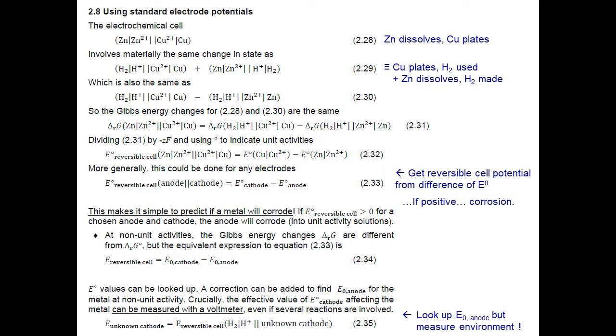But that doesn't matter, because you can see in equation 2.35, what I've done is I've simply said we can measure the equilibrium potential of the cathode on whatever metal we have in our environment. That we just need to use one measurement with a voltmeter connected between a standard hydrogen cell, in principle, and the unknown cathode that we're looking at, and then we know the cathode equilibrium potential. And then that means that with one measurement and one equation, 2.34, we can calculate whether a metal in any case corrodes.